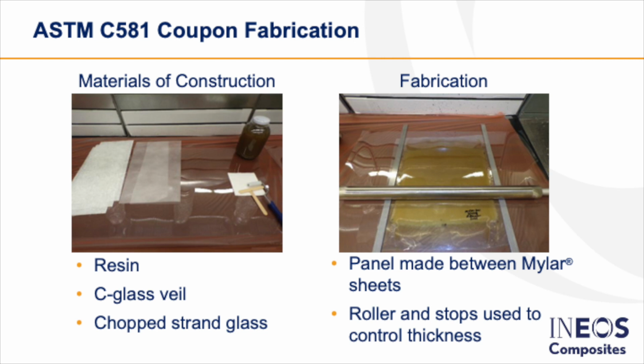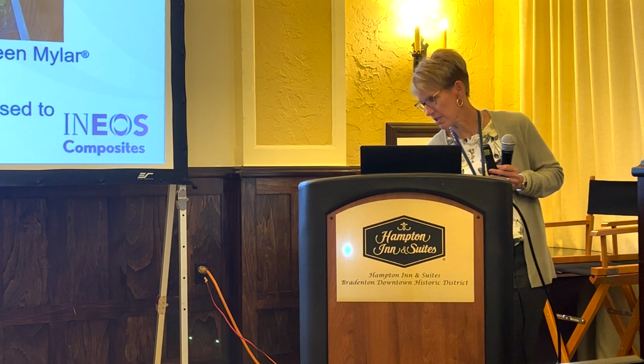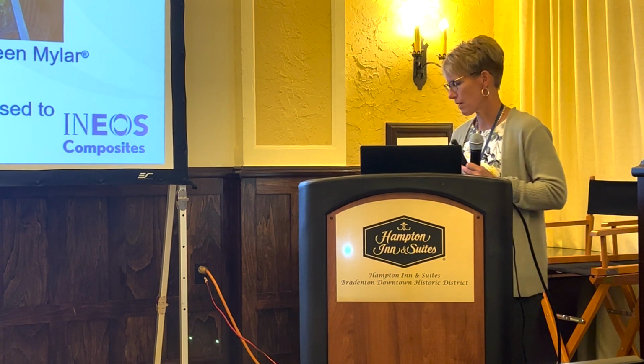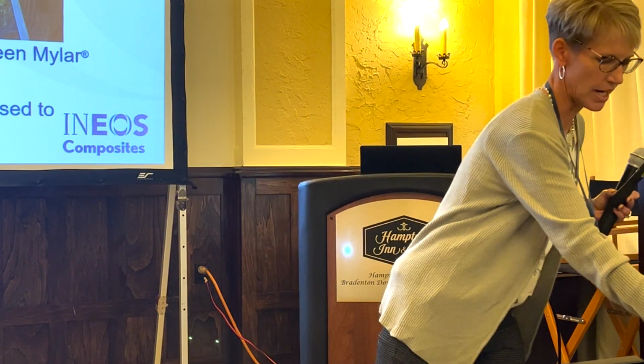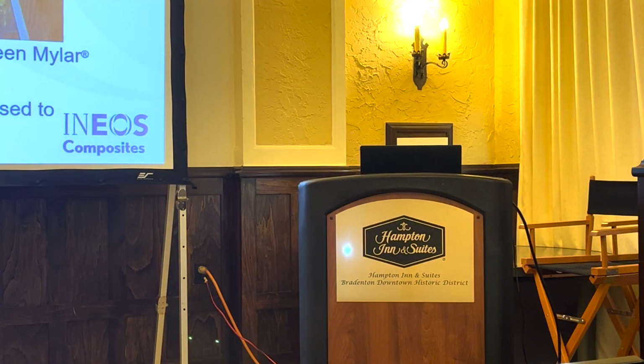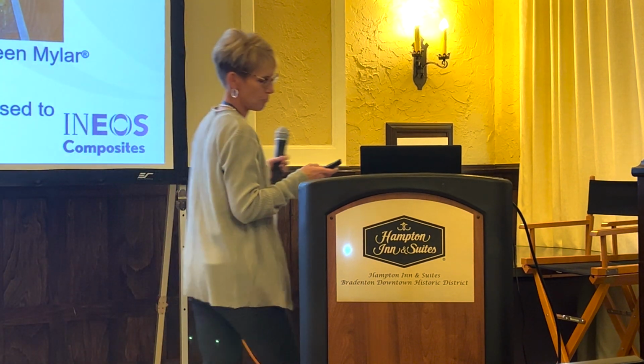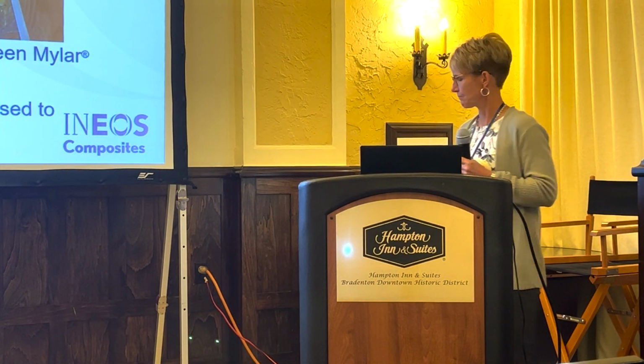This is just a picture of what we would do in the laboratory to make the coupons. We've got the chopped strand mat and the veil, and then your resin, and then here, just showing you how we would roll out the laminate using the stops to make a very even thickness throughout. And I actually brought a couple samples of the coupons that we would make. You can just pass those around. Just gives you an idea of what we can make and then supply to you if you need them to put in your environment.